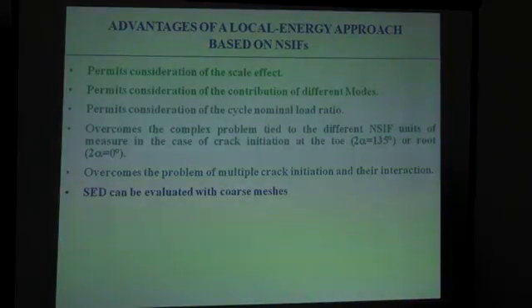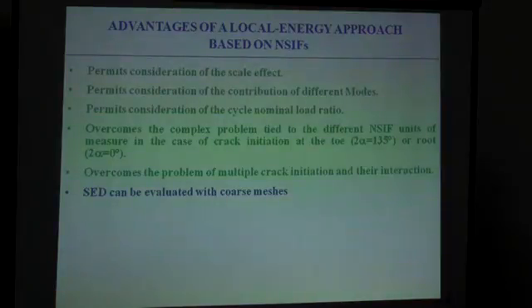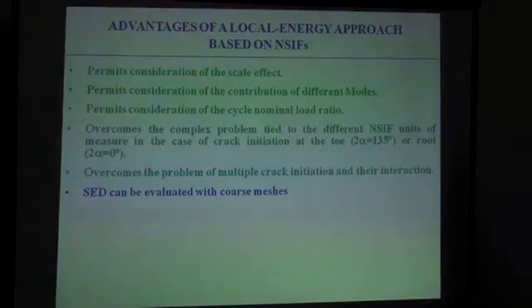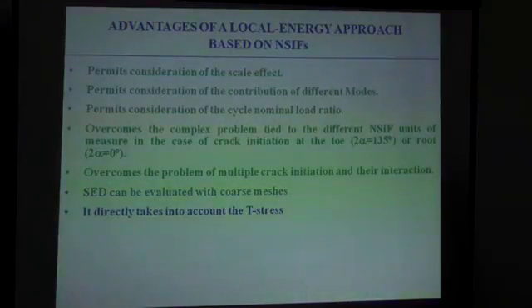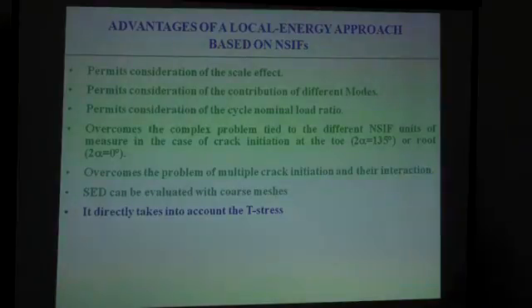SED can be calculated with a coarse mesh, and this is a strong advantage if we compare the method with the notch stress intensity factor, which requires a fine mesh for the calculation. It directly can take into account the T-stress if we consider a volume of material able to capture also this effect.